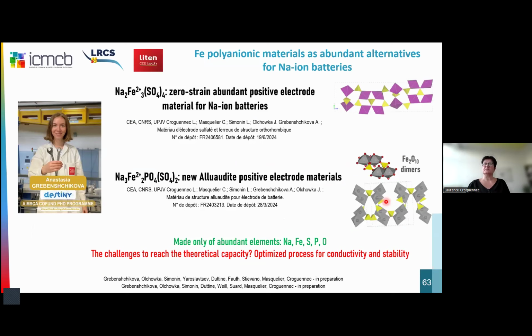And I will finish by mentioning also that it's worth, of course, to consider much more abundant materials, such as iron polyanionic materials. And especially here, I focus on sulfate and sulfate-phosphate materials. We found new phases recently. And of course, the challenge here is really to stabilize and optimize these materials in order to have very good performances. But they are very interesting because here we have sodium, iron, and sulfur or phosphate systems, so only abundant elements.